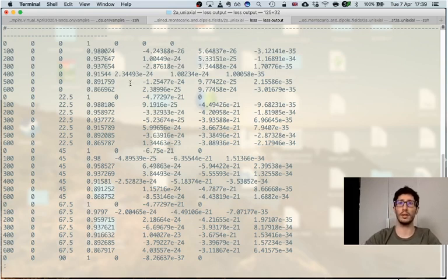Now the torque, because of the geometry and how the constraint is applied always along z, will be always along the y direction, while the x and z will be just noise. So we will be looking at this component here, in this case the sixth column of our simulation, and we can see we end up at 90 degrees.